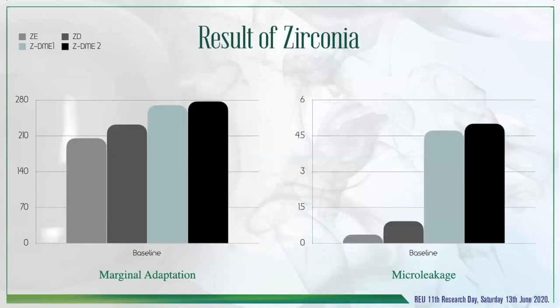As for the zirconia, we found the enamel and dentin finish lines had no significant difference, but both of them had a significantly lower vertical marginal gap than the 2 DME groups. As for microleakage, enamel showed significantly lower than the rest of the groups, followed by the dentin, and then the deep marginal elevation 1 and 2 showed significantly higher than the rest, with no significant difference between them. As for the zirconia, 12 out of the 40 zirconia samples debonded during the chewing simulation, so the comparison at the 500,000 cycle and 1,200,000 cycle wasn't applicable.